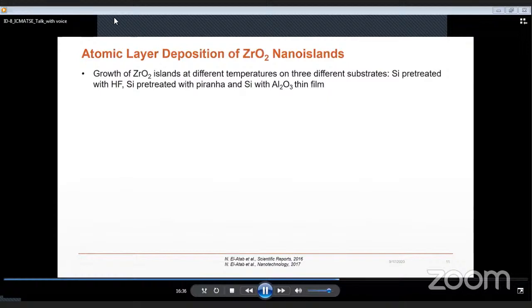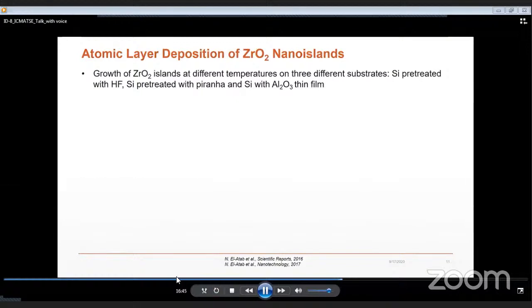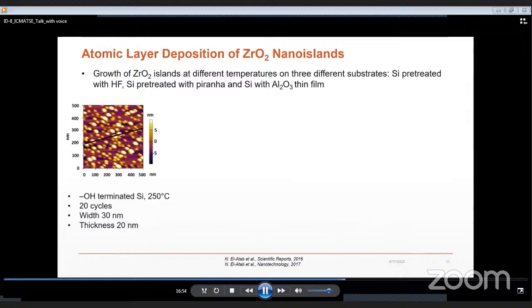The growth of the islands has been conducted on different surface terminations. So we have silicon etched with HF, silicon with native silicon dioxide, and silicon with a thin ALD-deposited aluminum oxide layer. Different growth temperatures and numbers of cycles were studied as well. On the sample with the aluminum oxide layer, which is OH terminated, hydroxyl terminated, and which is the case of the memory, we observed that with 20 ALD cycles at 250 degrees Celsius, large islands which are widely dispersed are obtained.